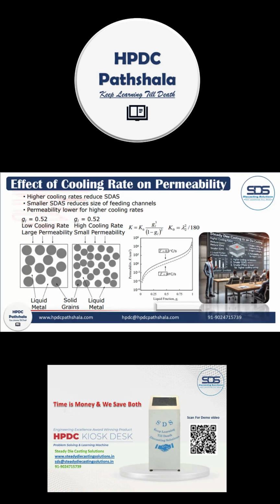SDAS stands for secondary dendrite arm spacing. So a higher cooling rate reduces SDAS, leading to smaller feeding channels in the mushy zone. As a result, permeability is lower because the gaps between the solidified grains are smaller and less interconnected.